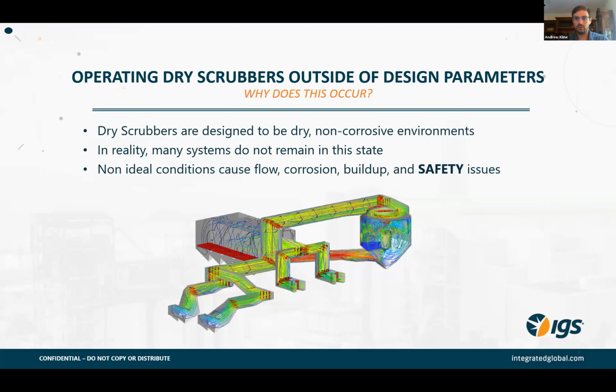So we all know the basics on dry scrubbers. They're designed to be dry. They're not supposed to have any aqueous solution hitting the wall, any moisture, anything like that. So most of the OEMs made them out of carbon steel because it's cheaper and it should work. But as we all know, this day and age, we have cycled loading, we've got low loading conditions, we've got economic reserves, different injections for different reasons, some emissions control, some efficiencies. All of these things can change the chemistries and the environment in the SDA, and that can lead to a lot of these corrosion issues.